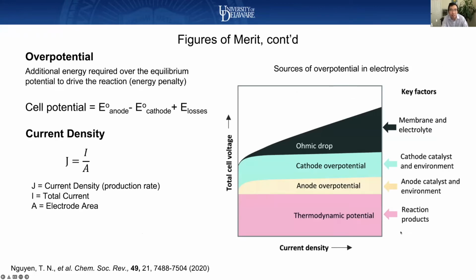The other consideration we have to keep in mind is, of course, that overpotential is important. That's the energy penalty. At the same time, current density is also important. What is current density? Current density is the production rate. You can consider it just a rate function. And in practical applications, you want higher current density to minimize the capital investment. So what we really want is a system that can operate at minimal overpotential but extremely high current density. In reality, it's really hard to achieve both in a single system, so there's some trade-off we have to keep in mind.